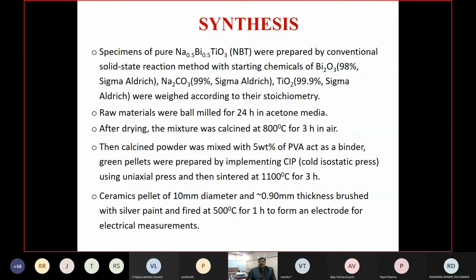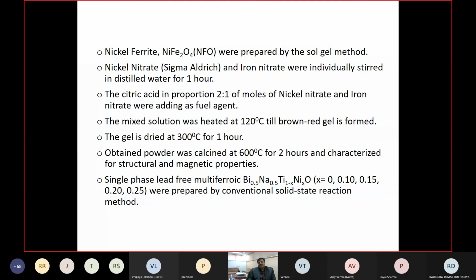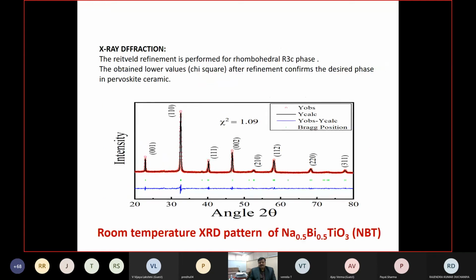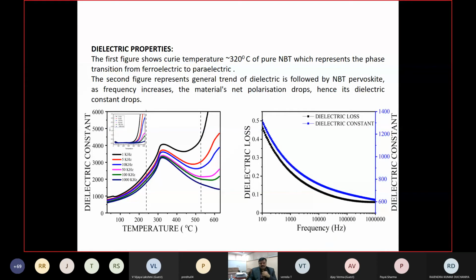So he used the same solid state reaction method to synthesize sodium bismuth titanate, but he used the sol-gel method to synthesize the nickel ferrite. So nickel ferrite he used as a magnetic material. So initially what he did, he took the NBT, that is sodium bismuth titanate, and took its XRD and got the rhombohedral phase, fitted with the Rietveld refinement, good refinement he observed, chi-square nearly 1. Then he took the dielectric properties, above 300 it is showing the ferroelectric to paraelectric behavior, and dielectric loss is very less, and you can see the dielectric constant is nearly 1400 at 100 Hertz.